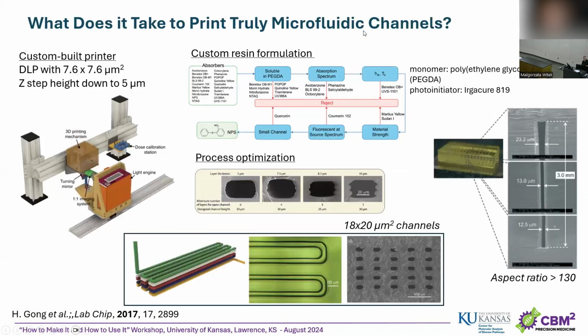Sorry. So this group at Brigham Young University built their own printer with DLP resolution down to 7.6 by 7.6 micron, with Z-step resolution of 5 micrometers, right? They also included in their setup dose calibration, so for specific resins they can calibrate what dose they want to use to achieve the perfect results that they're after, right? They tested multiple resin formulations. They looked through 20 different absorbers till they came up with one that was giving the best results, right?